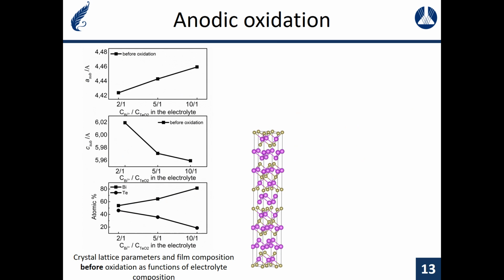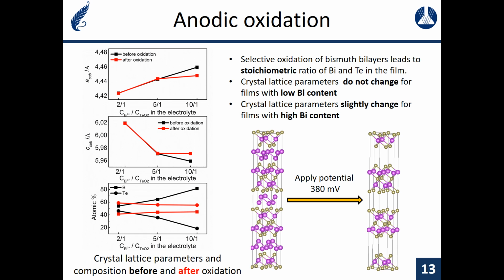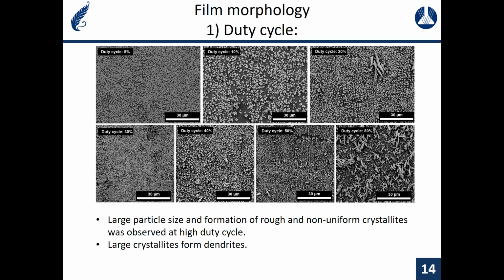We compared the effect of the anodic treatment at the potential of bismuth bilayer anodic oxidation at different bismuth content in the electrodeposited films. As this slide shows, the composition of the films become equal after the oxidation. The composition after the oxidation corresponds to stoichiometric bismuth telluride, while lattice parameters were not affected by the oxidative treatment, except the case of very high initial bismuth content.